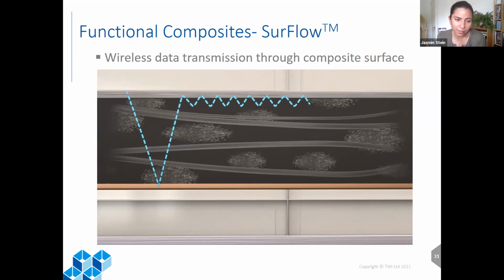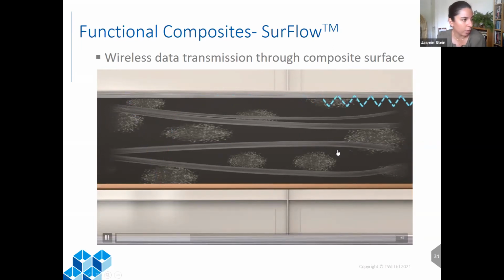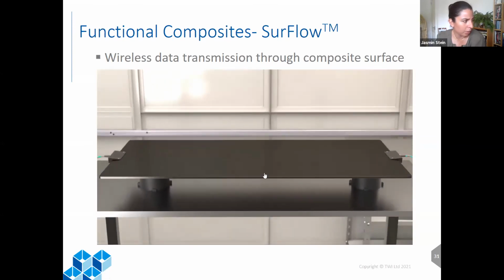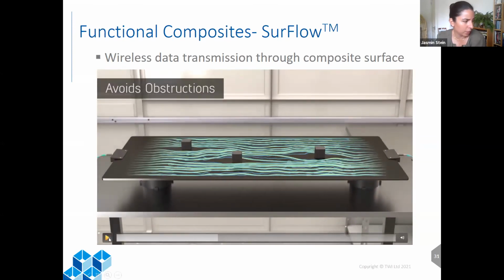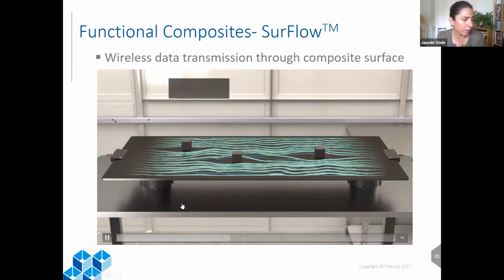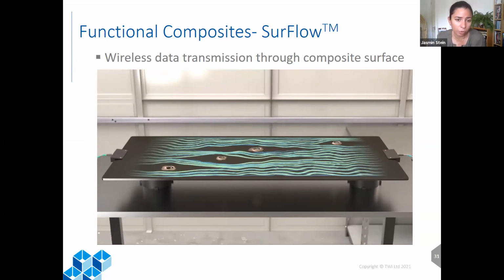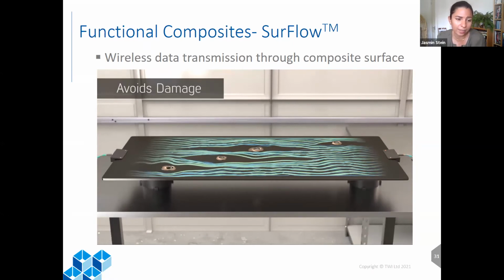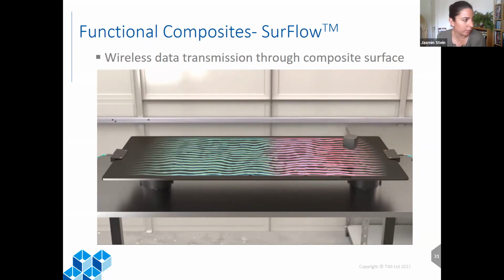The conductive layer doesn't actually carry the signal, but it prevents the signal from escaping the other surface. So the signal propagates from left to right. The advantage is because it's an electromagnetic waveform. As long as there is a continuous path, the signal will find a way, even if there is an obstruction or if there is a damage. So unlike a cable, where if the cable is broken, you would lose the signal. Here, as long as there is a continuous path, you still will receive the signal.